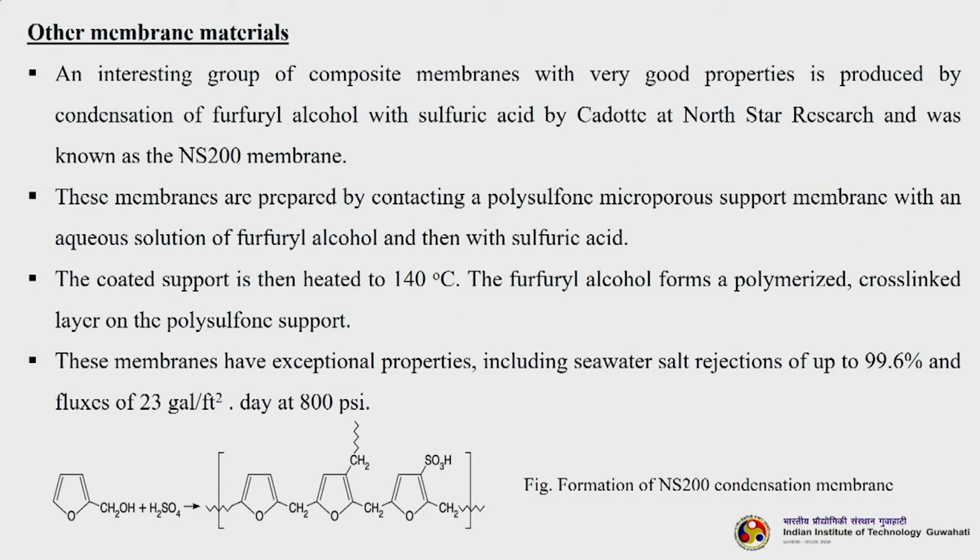Among other membrane materials, an interesting group of composite membranes with very good properties is produced by condensation of furfuryl alcohol with sulfuric acid by Cadotte at North Star Research and was known as the NS200 membrane, the trade name. These membranes are prepared by contacting a polysulfone microporous support with an aqueous solution of furfuryl alcohol and then with sulfuric acid. The coated support is then heated to 140 degrees centigrade. The furfuryl alcohol forms a polymerized cross-linked layer on the polysulfone support.